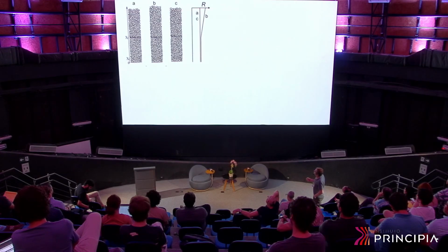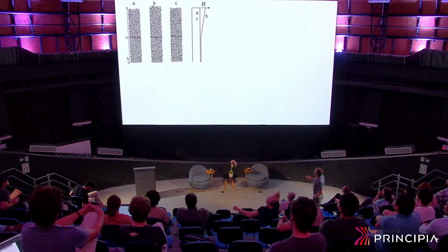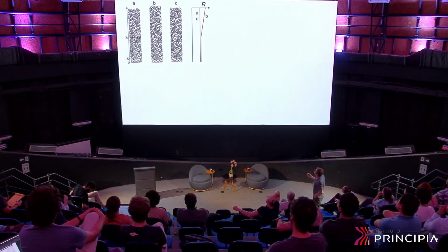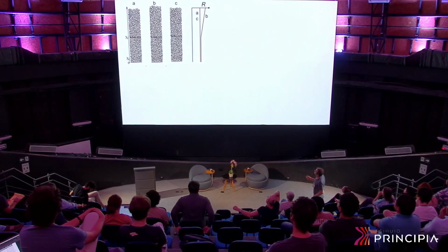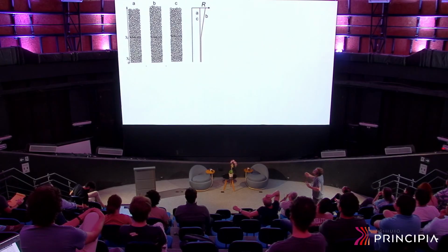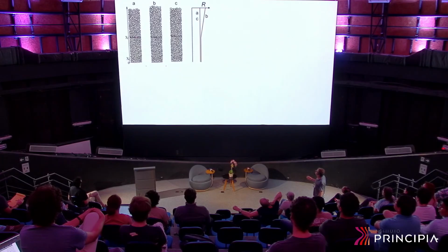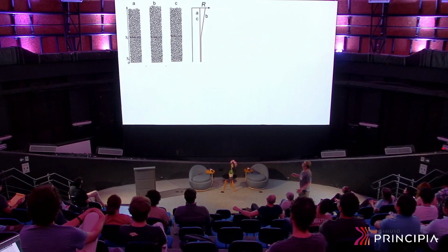So we did the simulation considering that we start with this configuration with some distribution of radius of the particles, and from here to here, let's say we multiply the radius of the particle by a function that is this linear profile here. So we are increasing the size of the particles at the top, mimicking a thermal expansion, and we consider that the effect decreases as a function of depth, so it vanishes completely here. So up to here, the particles are exactly as they were before, and from here we take a linear profile of modification of the radius of the particles.